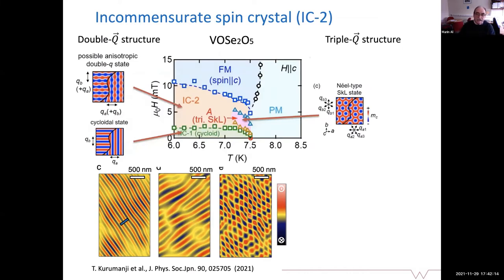So finally, we end up exactly in that type of skyrmionic phase, which was actually proposed by Tokura's group. They said, okay, we have this skyrmionic phase here, this pocket, but this skyrmionic phase is actually embedded in 2 other types of phases. This is the so-called IC1. It's a cycloidal phase. It's a cycloidal state. It's a stripe domain. It's one Q domain, which may be perpendicular, but not perpendicular at the same time, in the same place.